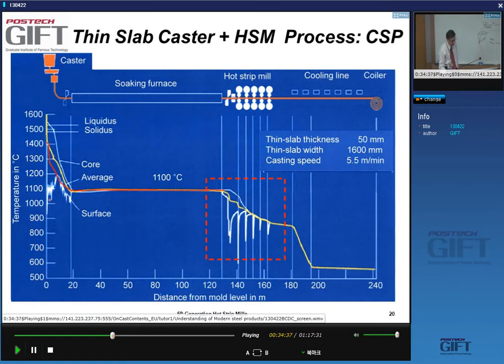You see the temperatures, yes? Let's say typical carbon steels. I'm sorry, but the line is not very straight. But you basically keep the material in the austenite temperature range, and you never go through transformations. In a normal conventional steel plant, after the casting, you go down and back up, so you have two transformations, yes?